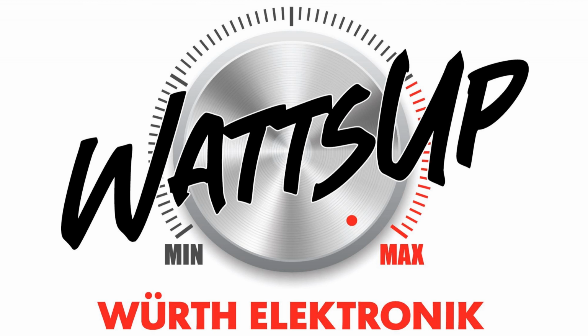Consider for a moment the WE CBF compared to the CBF-HF, which again is high frequency, where both are size 0603 of type wide band, and they have a peak of around 2.2 kiloohms. After the SRF, the ferrite bead becomes capacitive, and this effect of parasitic capacitances can be observed from their reactance behavior, as the value is no longer rising, but instead it's falling. For the WE CBF, the parasitic capacitance becomes dominant at 100 megahertz, while the WE CBF-HF dominates at 450 megahertz, shifting nearly 5 times higher in frequency than our standard part.